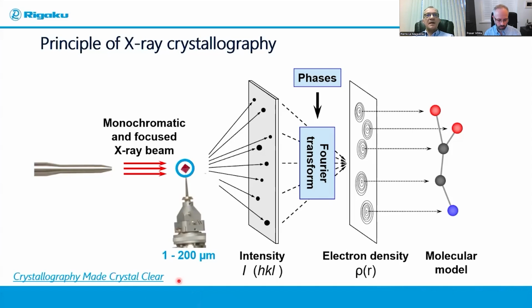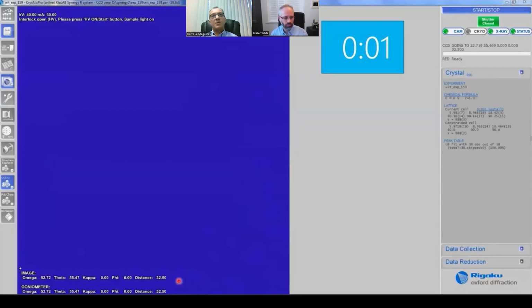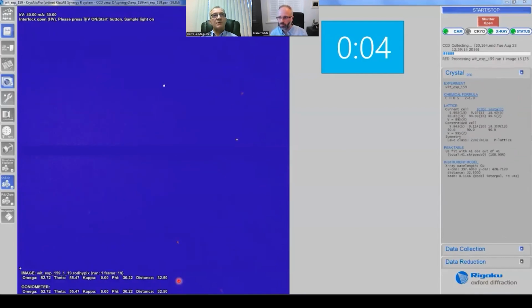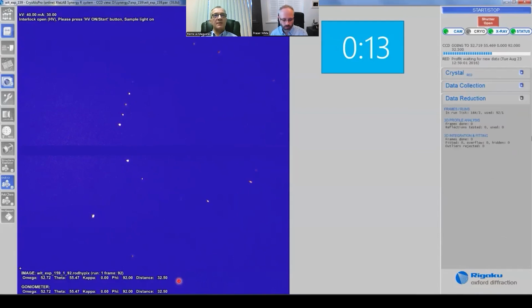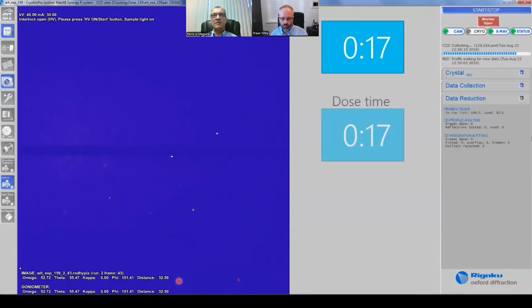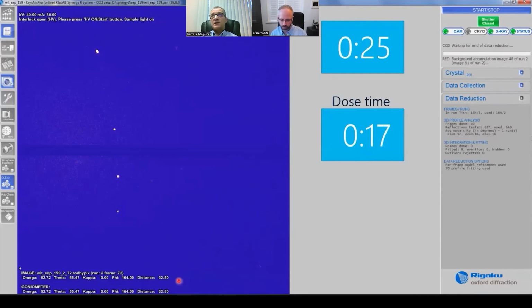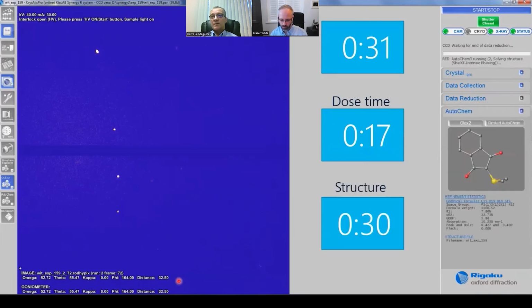This is how a typical X-ray diffraction experiment should look. On the left-hand side of your screen, this is an image of the detector, and you see that the reflections, those white dots, are recorded on the face of the detector, both their location and their intensity. On the right-hand side, the program then starts reducing the data, basically integrating the intensity of those reflections. And once the data reduction is complete, the program will then try to solve the crystal structure of your compound. And hopefully you get a good model for your compound. Now, it doesn't have to be a complete model every time, but at least a pretty good starting model that you can then quickly finish up manually. You will be surprised how often it works that way from the moment that you can grow a decent crystal.